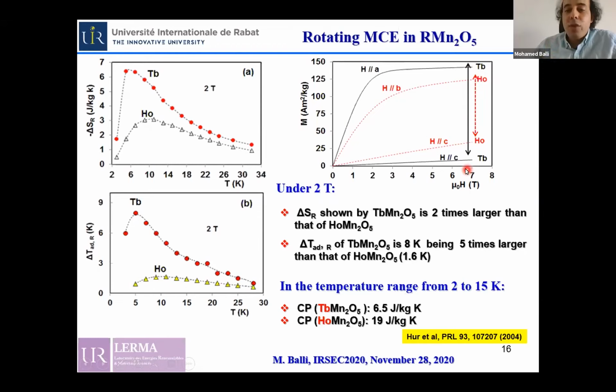There is another interesting point. In addition to all these factors, the specific heat of terbium compound is much lower, as you can see here, than that exhibited by the holmium compound. This is mainly due to the fact that the magnetic moments of terbium compound are more ordered, lowering the contributions from the magnetic specific heat.